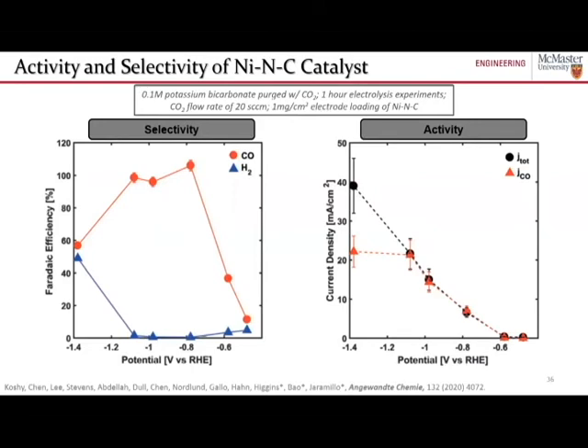So when we took these nickel nitrogen carbon nanoflower catalysts and put them on an electrode and tested them for the electrochemical CO2 reduction, what we found is that at electrochemical potentials between about minus 0.7 volts versus the RHE and minus 1.1 volts versus the RHE, we could get near unity selectivity towards carbon monoxide. So pretty much 100% selectivity towards carbon monoxide.